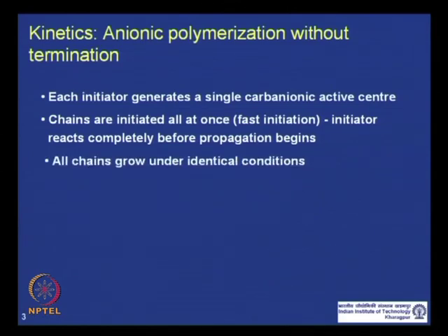And as you can now visualize, after the initiation is complete, all the chains will grow simultaneously under identical conditions, and unless we have any impurities or we want to stop or terminate the reaction by adding some agent, there is no termination reaction. Actually, there is no or very little depolymerization reaction, depending on the ceiling temperature of the polymer as well.